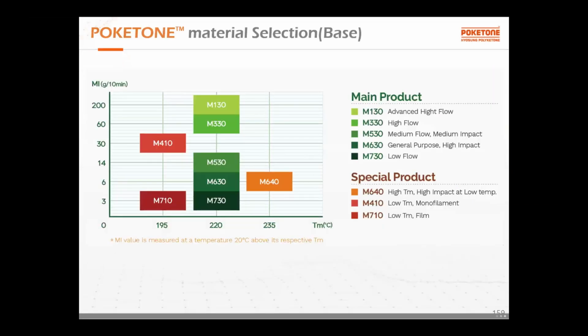This is the base resin portfolio of our polyketone. Polyketone can be categorized based on the melt flow index and melt temperature. Our main grade is the melt temperature is around 220. And we have 5 grades from low viscosity M130 to high viscosity M730. We also have special products like M640, which has a higher melt temperature, and M410 and M710 is the lower melt temperature, by adjusting the propylene content.